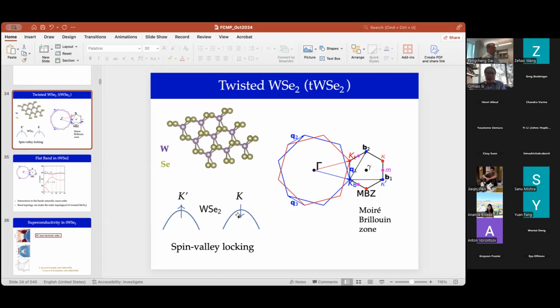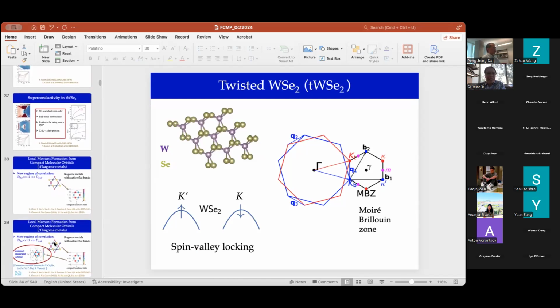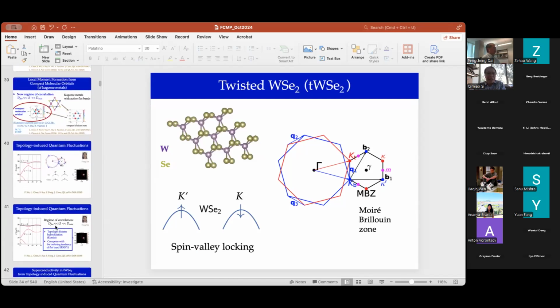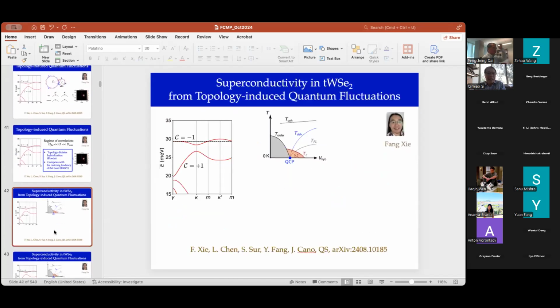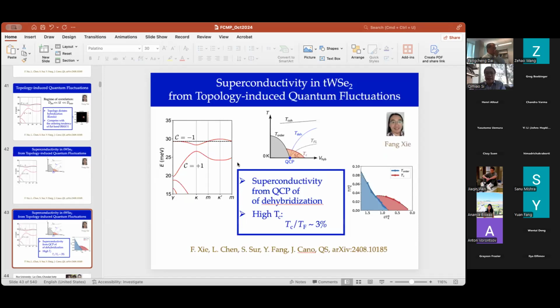That's an issue that is not clarified. In our calculation, we have this electronic order, a real space orbital sitting on the triangular lattice, and there's spin-spin interactions because that orbital is close to half filling. So in our calculation, this is antiferromagnetic order. But I think to interface with what's going on with real material, there's still some time to be.